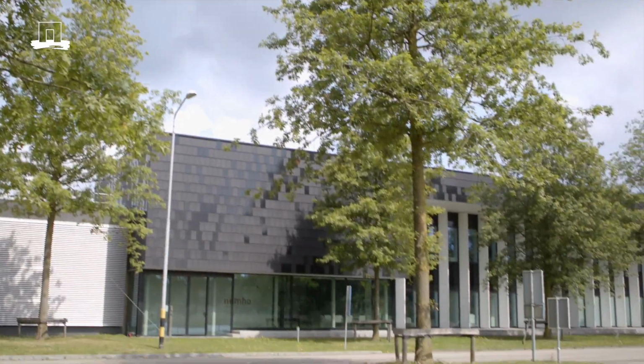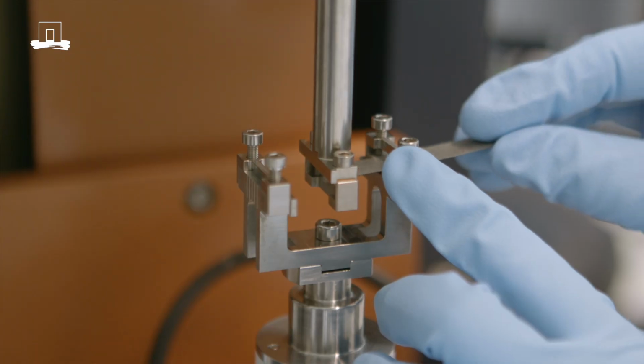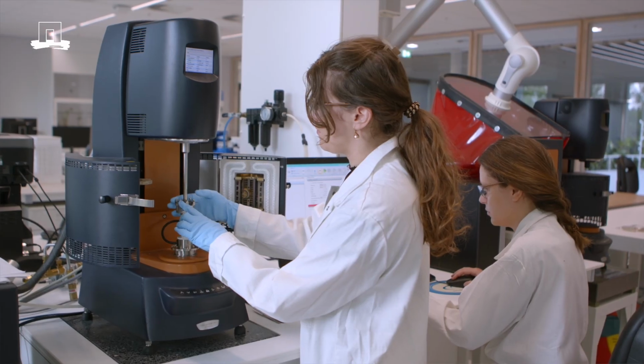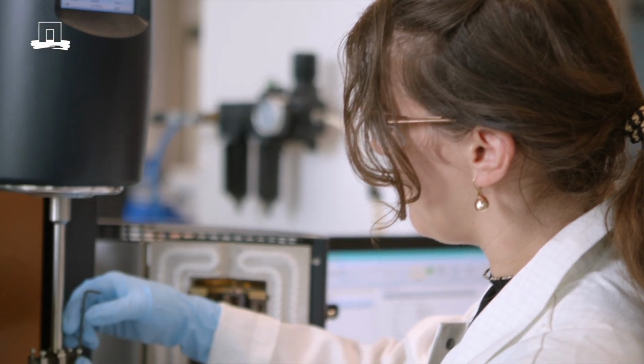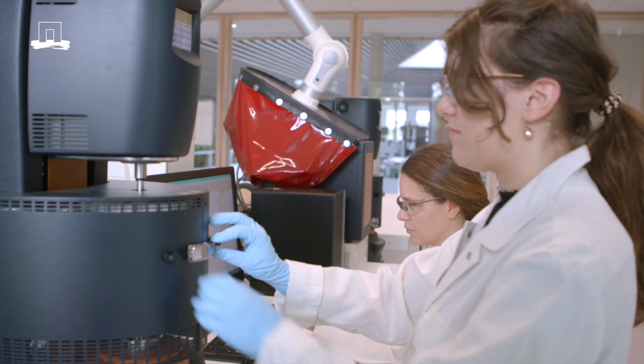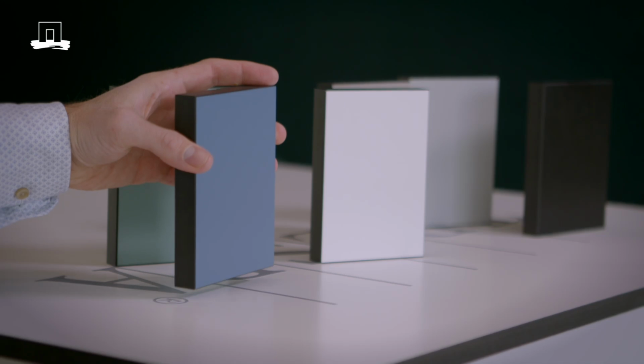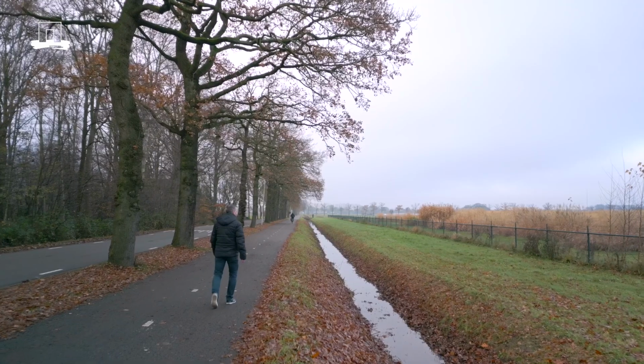At the NIM R&D Center, we collaborated with Wageningen University Research to replace part of the fossil-based phenols within our resins with refined lignin, a natural adhesive. We were looking for a sustainable choice without compromising the performance of the product. The result is this innovative product for worktop surfaces that incorporates up to 85% bio-based carbon content.